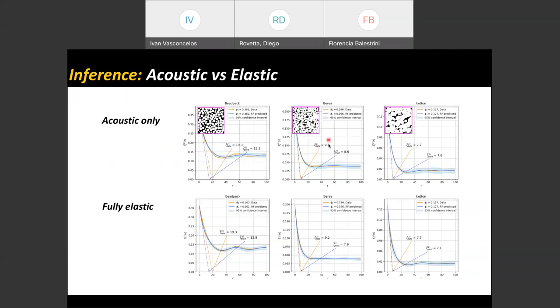Notice that, for example, if we look at the sandstone here, both the acoustic and the elastic give decent predictions of the two-point correlation functions, but the elastic does a better job and yields a tighter confidence interval. In some cases, like the case of the bead pack that you see right here, because the bead pack is oscillatory, this is much harder to constrain. You can see that acoustics fails to constrain the oscillations. In fact, the acoustic gives us a fairly biased answer here. We would be tempted to think that this is a well-resolved answer because the confidence intervals seem to be tight, but you can see this is a biased answer. Whereas by using the fully elastic data here at a range of frequencies, we constrain this much better.